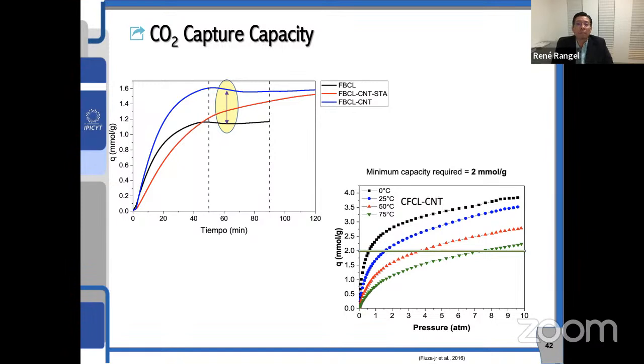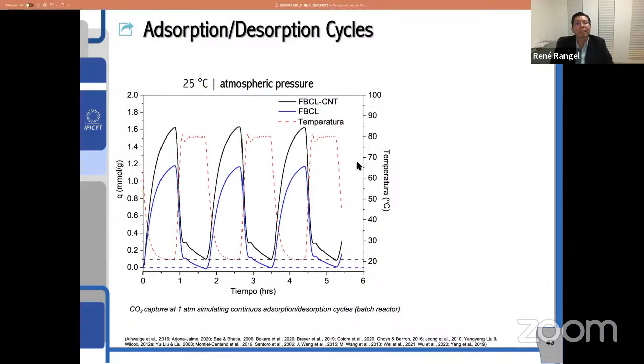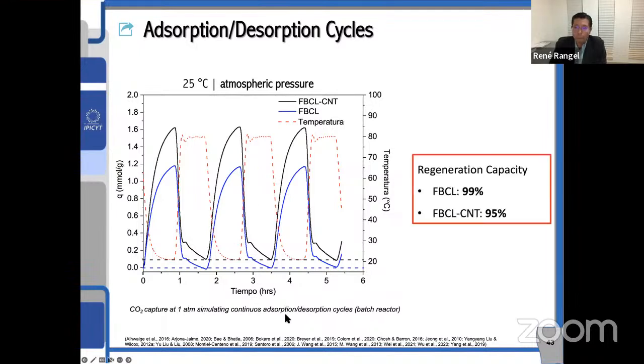Another question is, okay, is the material regenerable? Because otherwise it's not a good material. Well, in this case, at atmospheric pressure and 25 degrees, we have the cycles of absorption and desorption. And as you can see, again, the kinetics are very fast. When it goes up, it's absorption, and then desorption. Absorption, desorption. The regeneration capacity of the fibers is 99%, and the material with carbon nanotubes is 95%. But this is at 25 degrees. If we increase the temperature a little bit, the regeneration is 100%. This is also very good because we can reuse the material n times. That's very important.